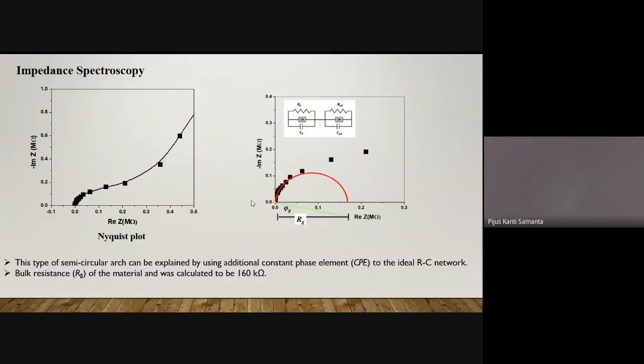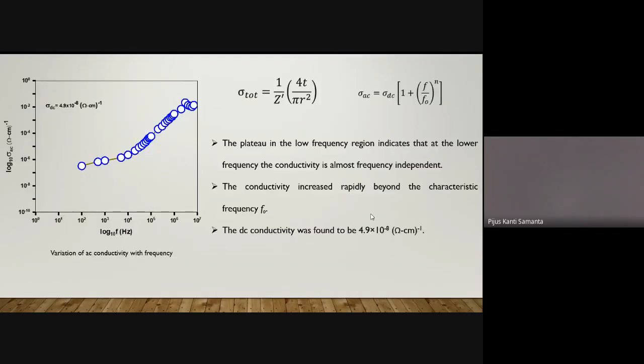And from this semicircular arc, we can find the bulk resistance of the material, that is from the bulk contribution. That was about 160 kilo ohm. And ideally, this circle should be an ideal circle centered at this zero axis. But we see a depression of the curve due to non-Debye type of relaxation process that can be incorporated by using an additional constant phase element into the equivalent RC network of the dielectric system.